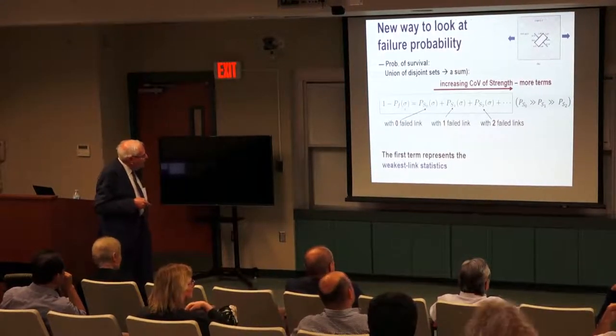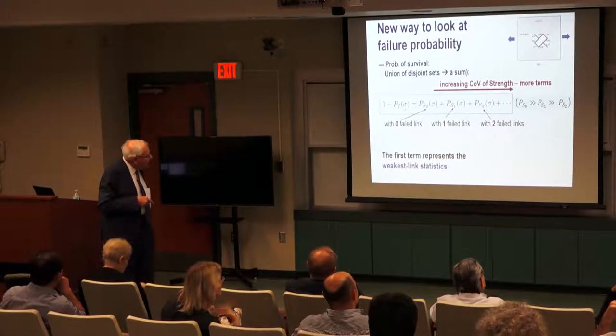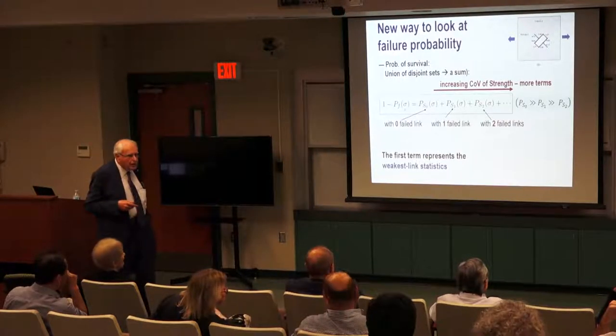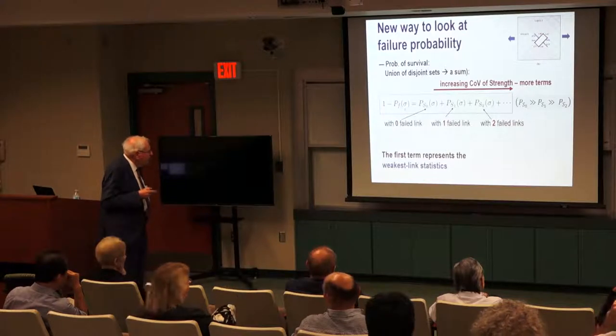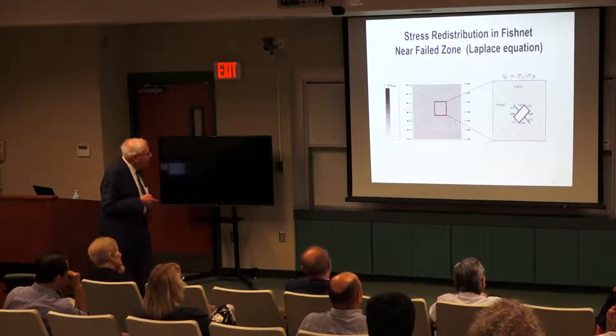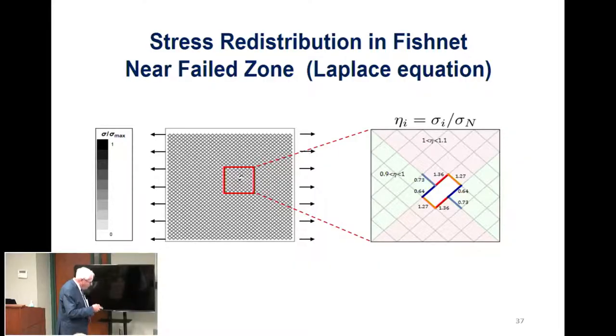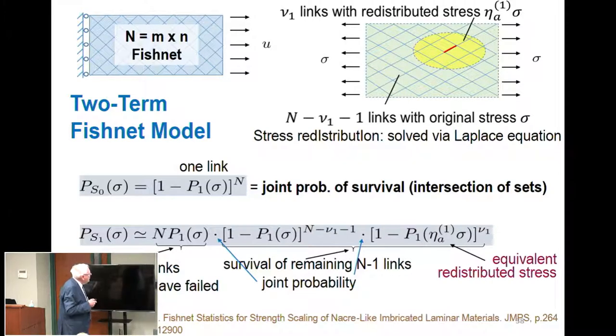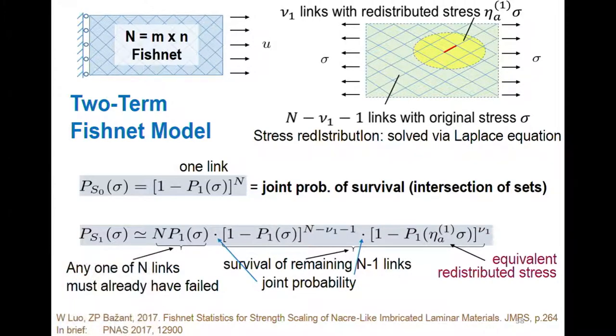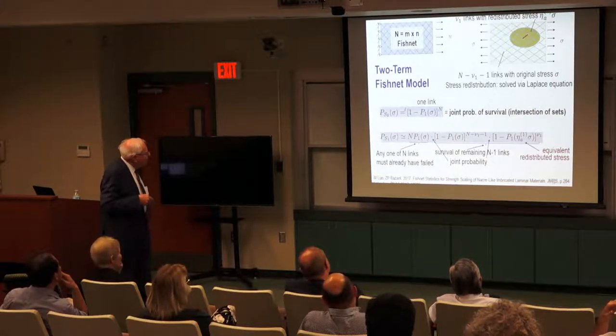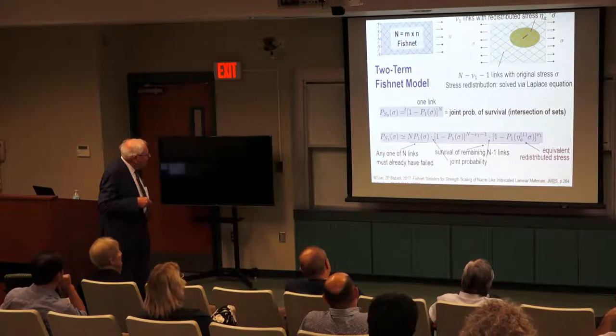Now, what is interesting about this sum is that these terms decrease rapidly. There are many failures with the first link, second, this is much bigger than that, and you really don't need more than about four terms. Even three terms is enough. And that can be calculated quite well. So the calculation involves some redistribution, which I mentioned here already. If one link fails, this is higher stress, then it decays. We replace this with a continuum, which goes to the Laplace equation. We calculate continuous redistribution and then project it into the mesh. So we get the calculations. And we consider fishnets of rectangular size with m rows and n columns, like this. And the simplest calculation is we consider up to two terms. So the first term is one link.